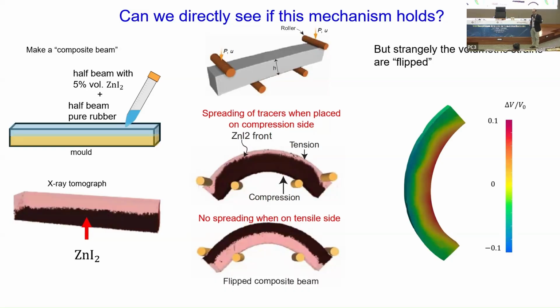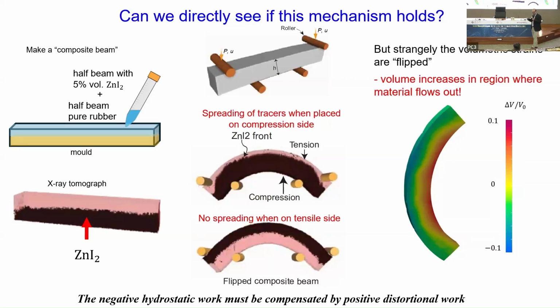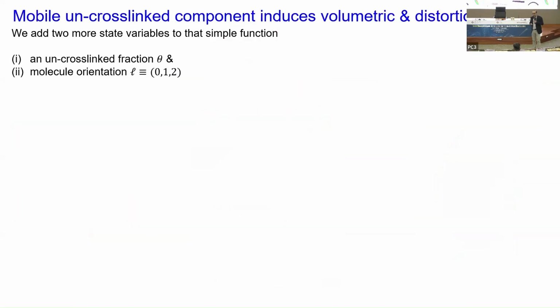And of course, this strange behavior remains, that you're getting this flipping, effectively, that you're getting the volume increasing on the side where this material is moving out from. Because what you can see here is that the material has moved from this compression side to the tension side. So the volume is increasing on the compression side, and the volume is also decreasing. So how can you explain that? Well, effectively, the negative hydrostatic work must be compensated by a positive shear work or distortional work.